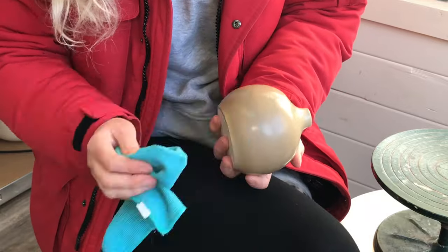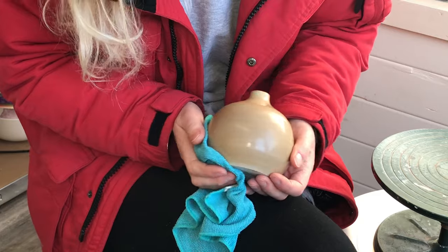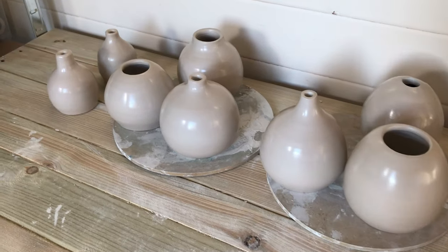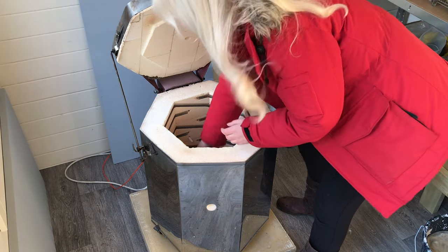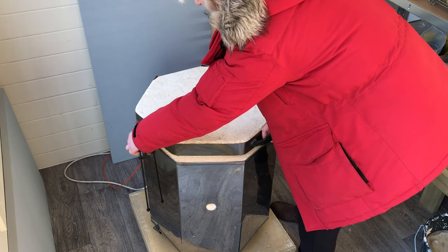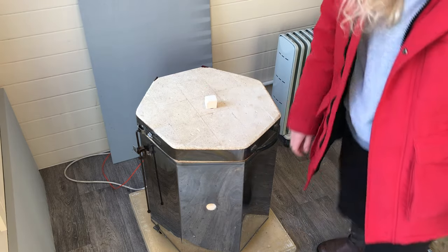As I say, this has been applied to bone-dry clay. These are the pots I'm going to fire in the saggar firing — they've all got a coating of terra sigillata on them. I'm loading up the electric kiln, and I do a three-hour preheat at 90 degrees centigrade or 194 degrees Fahrenheit the day before I bisque fire.